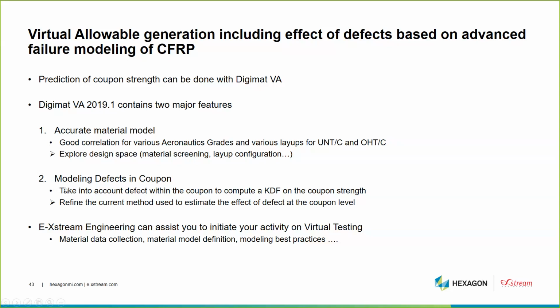The second major feature is the possibility to introduce a defect in the coupon. So here we have the possibility to take into account the defect in the coupon and to compute a knockdown factor on the coupon strength. We solve the coupon without the defect, we solve the coupon with the defect, and then we compare the strength. So this also allows us to refine the current method used to estimate the effect of this defect at the coupon level. It's a refinement on the way we compute this knockdown factor.